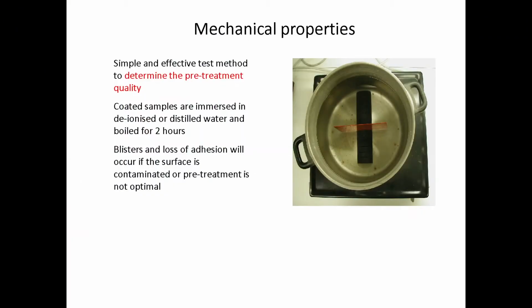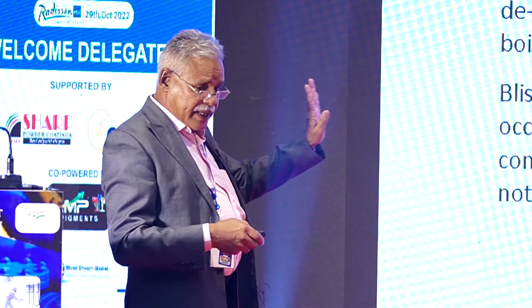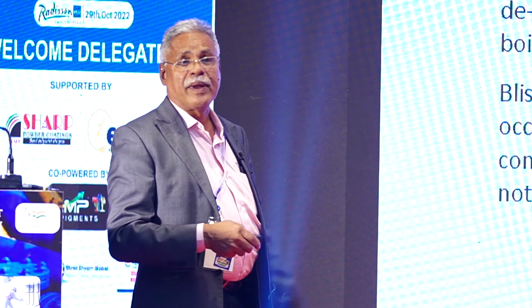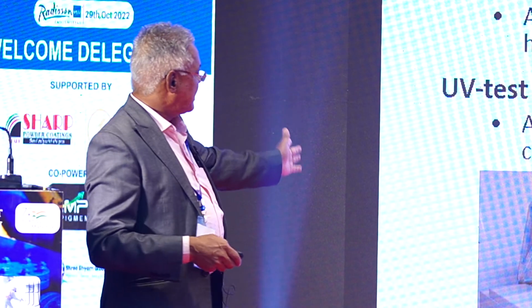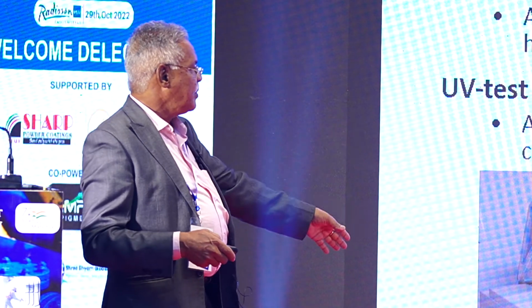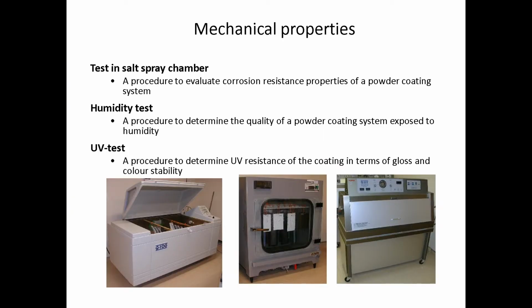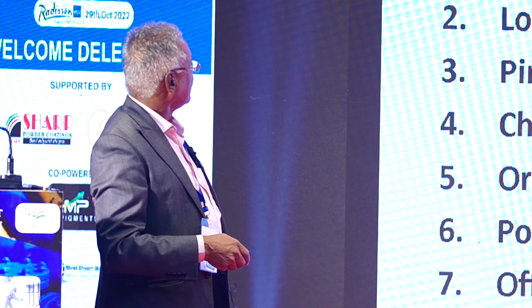This is a test method. Basically, when you boil a powder coating panel in distilled water for 2 hours, it should not form any blister or the film should not peel off. If it does, then the pre-treatment is the problem. So the test methods are salt spray, humidity test and UV test, QUV equipment. These are the things we have to go through.